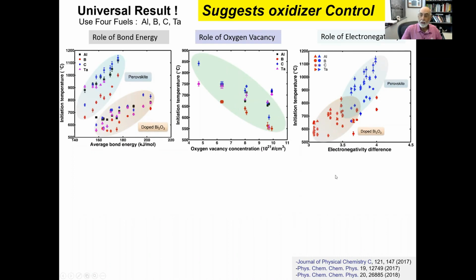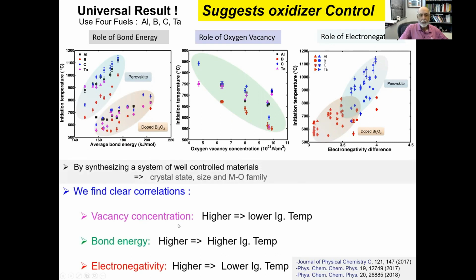And then the trend we start to see with electronegativity. Here are the perovskites with their electronegativity. The doped bismuth oxide have lower electronegativity differences, and their ignition temperature is lower. So, we have this family of curves that summarize that this behavior of the oxidizer is independent of fuel and correlates with the behavior microscopically of how oxygen can be tuned to move. So vacancy concentration, the higher the vacancy, the lower the ignition temperature. The bond energy, the higher the metal oxygen bond energy, the higher the ignition temperature. And the higher the electronegativity difference between the metal and the oxygen, the lower the ignition temperature.